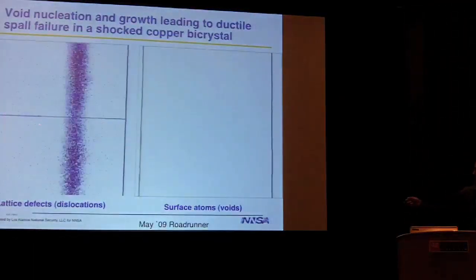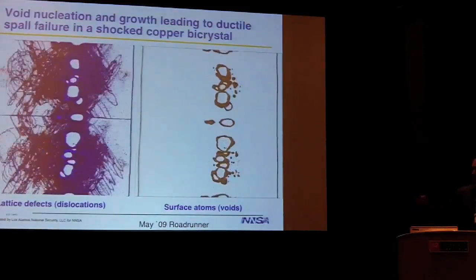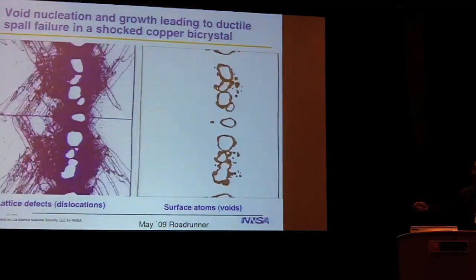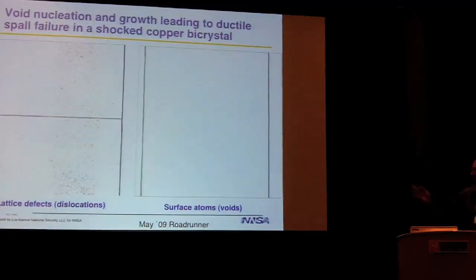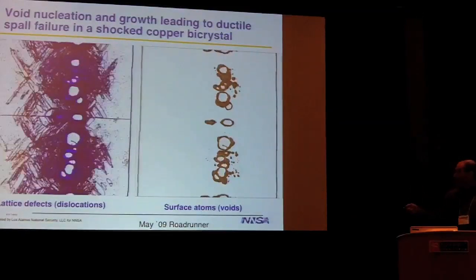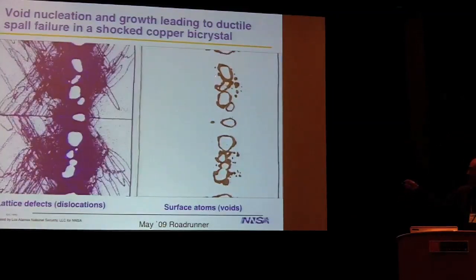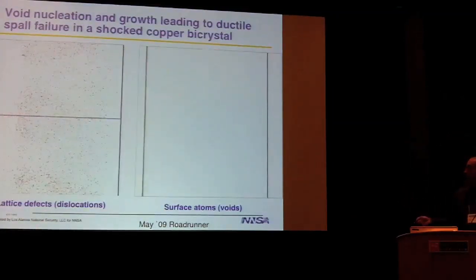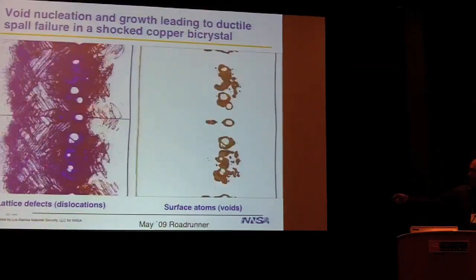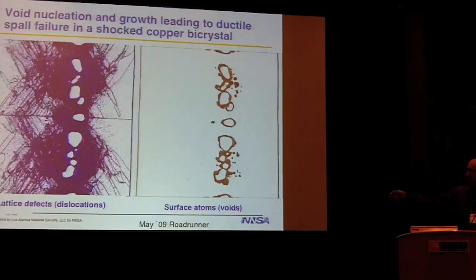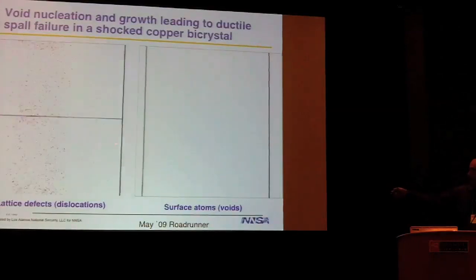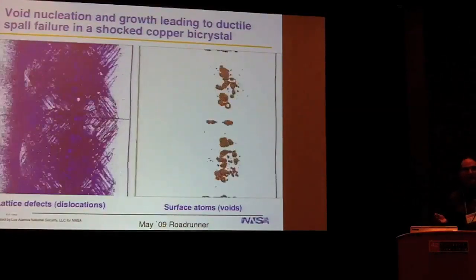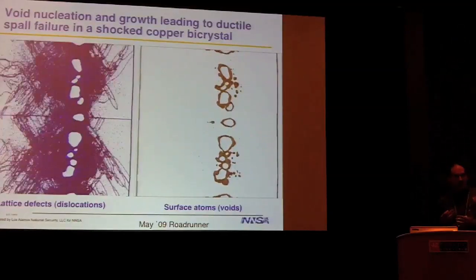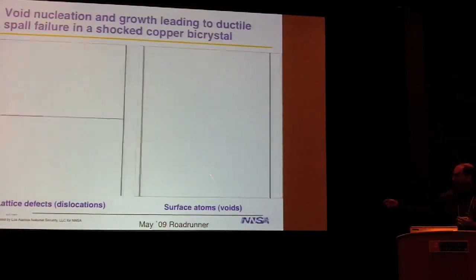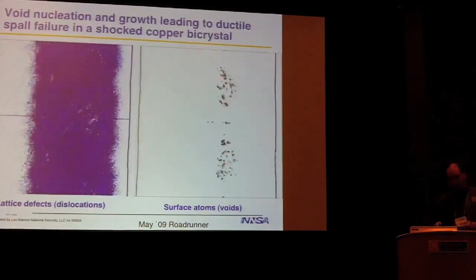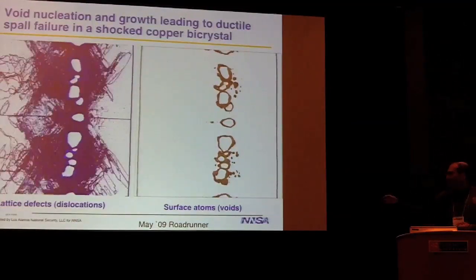Another example is, in this case, instead of looking at all the atoms, just looking at the defect atoms and seeing as a shock goes through and then an unloading wave comes through, how the material pulls apart and forms these voids and eventually fails by the nucleation of these defects, the dislocations I mentioned within the material, and then nucleating these voids that eventually link up and the material fails. So these are the types of single-scale simulations that are used to develop physical models for what tensile stress and temperature and strain rate materials fail